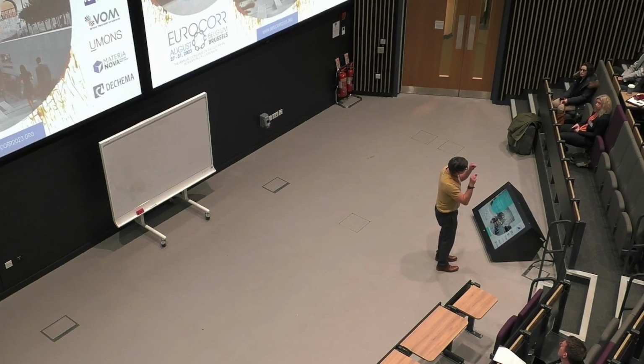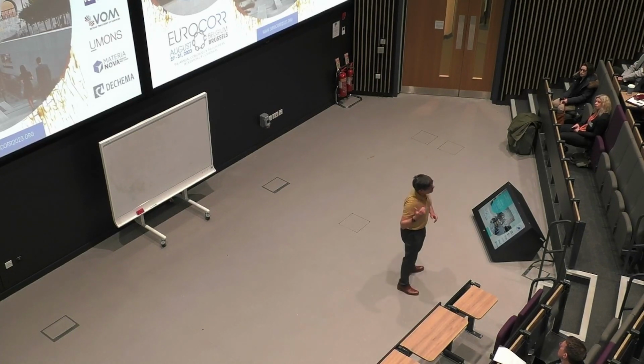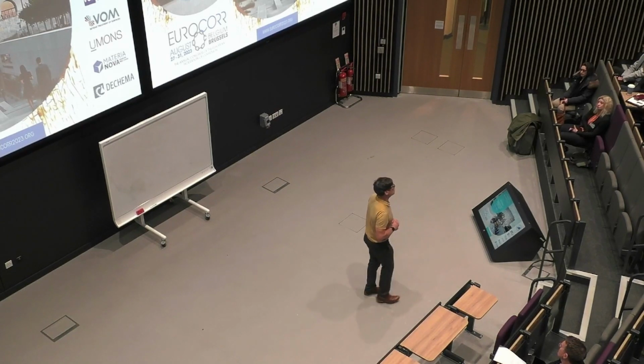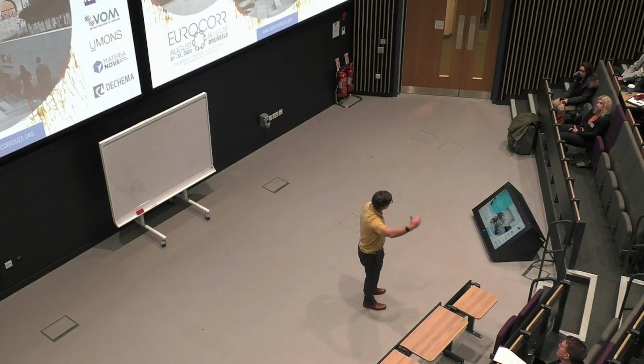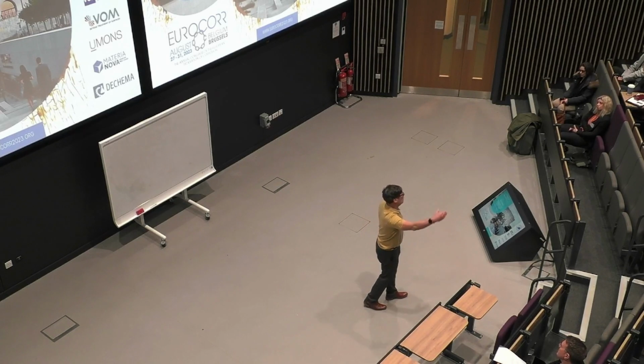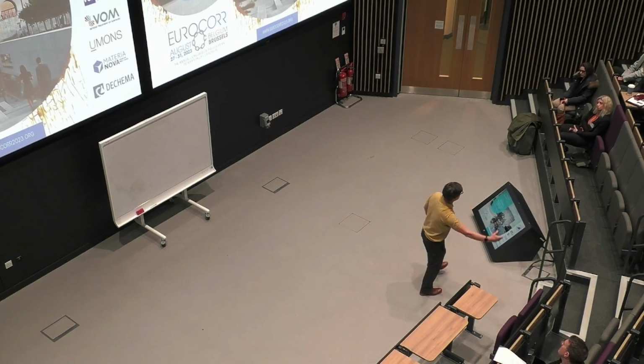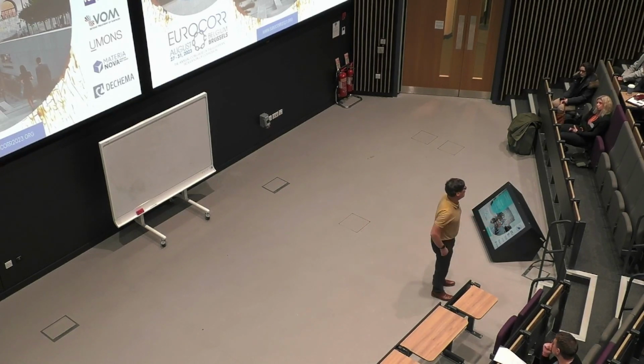And when we were making very thin layers, the correspondence was excellent. And we also did, I didn't have time to show you, near ambient XPS measurements to see, when you have exposure to moisture, what is happening with the interfacial bonding. And that was a very good fit.